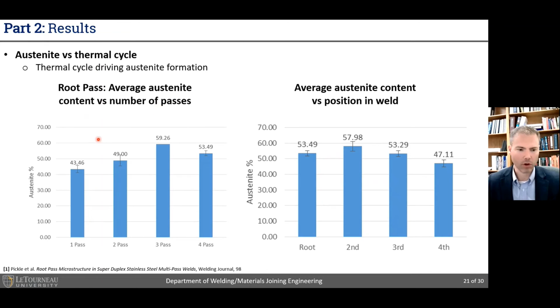As we look at plotting the austenite fraction as a function of the number of passes, you can see that it's maximized with the third pass before dropping slightly in the fourth pass. If we go through and just characterize the austenite content through position in the weld, we appear to find, consistent with this, the highest is in that second pass. It's unclear, perhaps this is driven by dilution effects from the surrounding base material, but the key point to take away is that these thermal cycles appear to be driving the microstructure evolution in the weld.